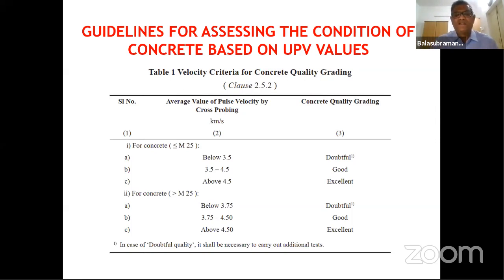So they have put some higher threshold numbers of 3.75 and above. Any velocity less than 3.75 is doubtful. Now, for consultants like us, any velocity less than 3.75 kilometers per second comes in the doubtful category, and then as a consultant, we have to give some methodology. Naturally we are going to say grout, but no grout will go inside for a velocity of 3.5 or 3.4.